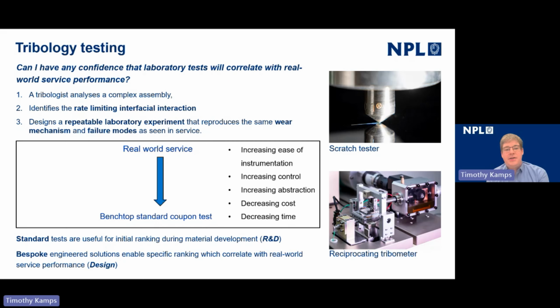But we increase the amount of abstraction from the real-world service to the benchtop test, and we have to be careful that as we reduce the number of input variables for the experiment, we don't actually remove the one that's causing the failure or the unexpected behavior. Of course, moving from a full assembly down to a benchtop standard test, we decrease the cost and decrease the time of instrumentation and experiments.